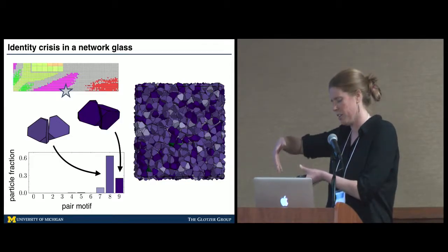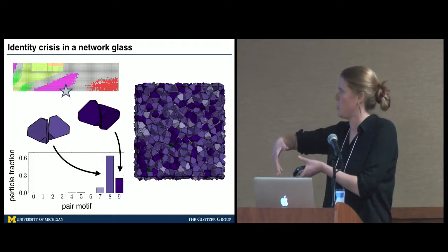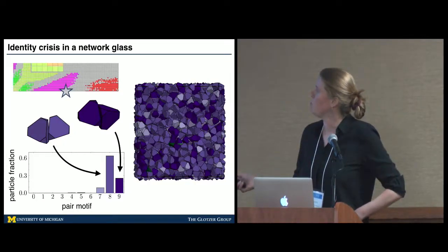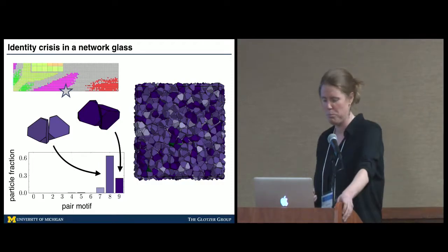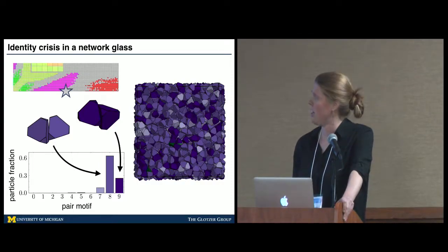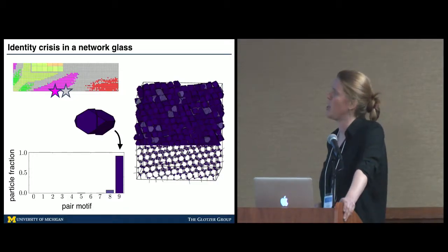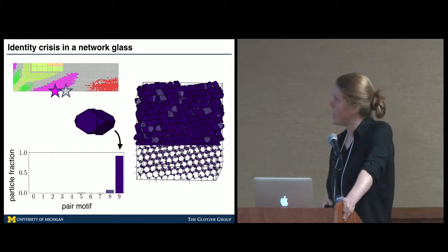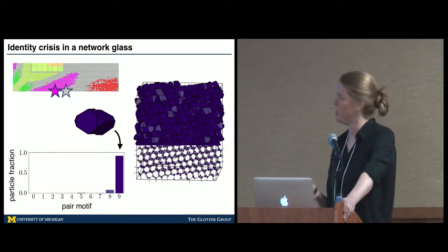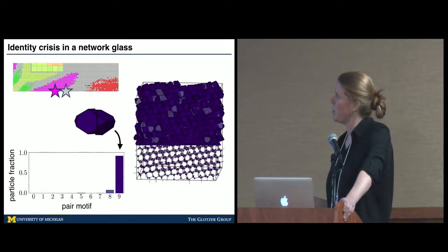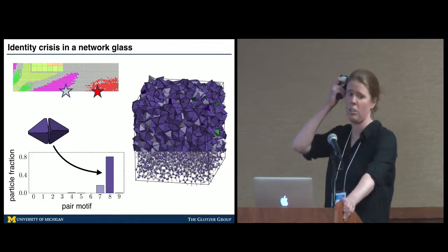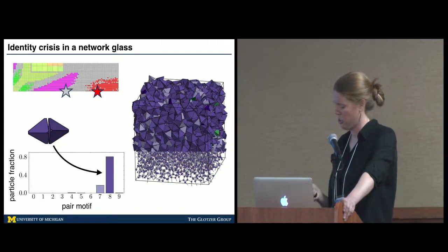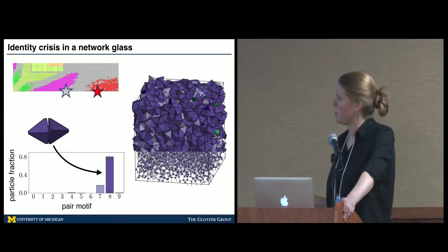These are basically two particles that are bonded face-to-face with each other. But the difference is that in one motif, there's a twist in one particle with respect to the other. So it's a really small difference, but a difference nevertheless. And if you look at nearby shapes in this shape landscape that do form ordered structures, you find that one motif or the other dominates in these ordered structures. So in a nearby point that forms diamond, you find the twisted motif dominating. And in a different nearby point that forms a dodecagonal quasicrystal, actually, which is a very fascinating structure in its own right, the non-twisted motif dominates.